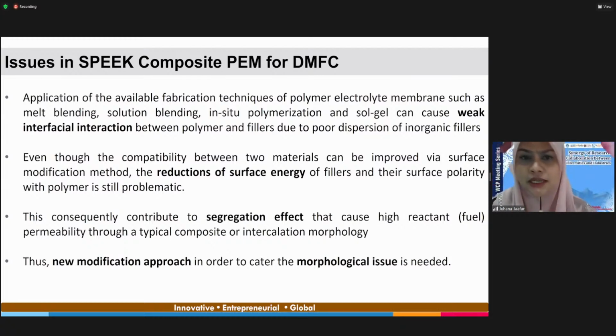Okay. So firstly, the application of the available fabrication techniques of polymer electrolyte membranes, such as melt blending, solution blending, in situ polymerization, and sol-gel, can cause weak interfacial interaction between the polymer and fillers due to poor dispersion of inorganic fillers. So there will be a gap between the polymer and the filler. The filler is normally inorganic, and the polymer is organic. And even though the compatibility between the two materials can be improved via surface modification methods, the reduction of surface energy of fillers and their surface polarity with the polymer is still problematic. This is still closely related to the compatibility issue between the polymer and the inorganic filler that we choose.